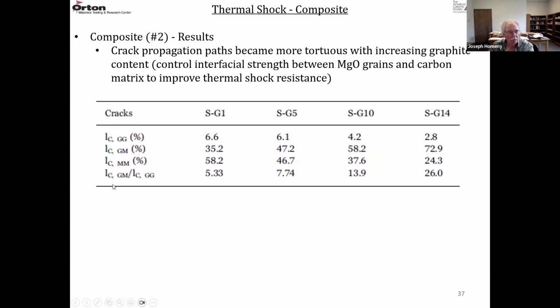So they looked at these values here. The proportion in the coarse grains, the proportion in the interface, and the proportion in the matrix for all 4 of these. So the crack propagation path became more tortuous as the graphite content increased. So this is in the coarse grains. SG1, 6 or 7% of that crack path was through an MgO grain. But if you go across the higher graphite contents, it's down to 2.8%.